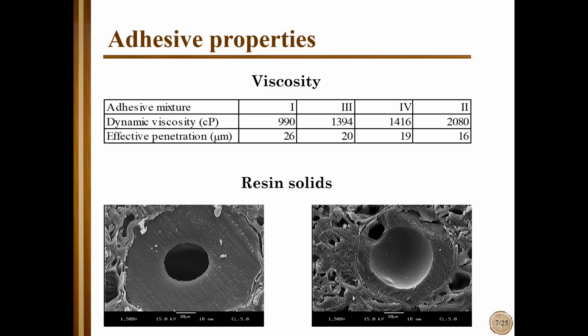Here you see two pictures of scanning electron microscopy. You see that a lot of adhesive shrinks during the curing. Generally speaking, let's say half of thermosetting adhesive is water. So this water evaporates during curing, and adhesive will shrink. On this left hand side photo, you see an opening which was created later when adhesive cured and shrank. On the right side, you see a crater. This is actually an air bubble inside of adhesive, which is in the vessel of beech wood.